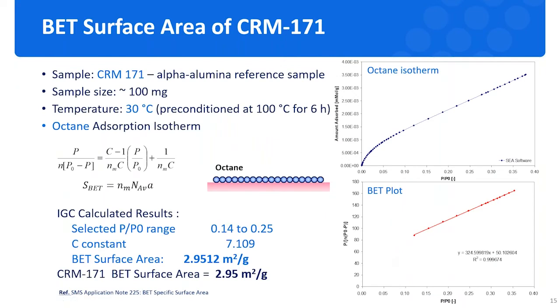So just an example with a certified reference BET material that we bought from the market, that is the alpha alumina reference material, CRM171. We performed the BET surface area determination with the IGC technique with about 100 milligram of the sample packed into the column. Then we preconditioned the sample at 100 degrees for 6 hours. Then we performed the experiment with octane isotherm at 30 degrees. So here we show the octane isotherm for the material, which is a really good type 2 isotherm. Then we can apply exactly the same condition as the volumetric nitrogen sorption with the monolayer coverage.